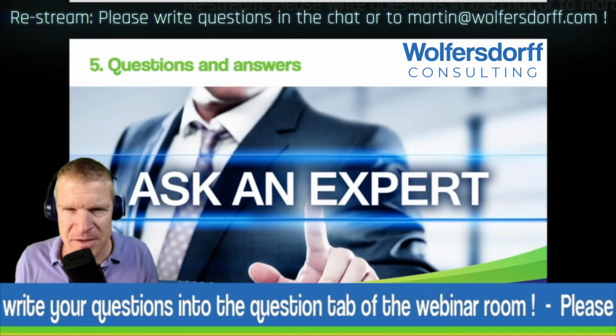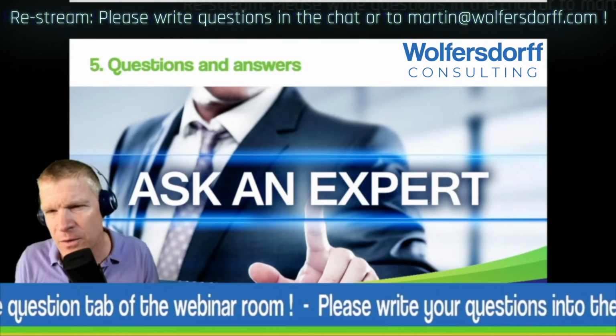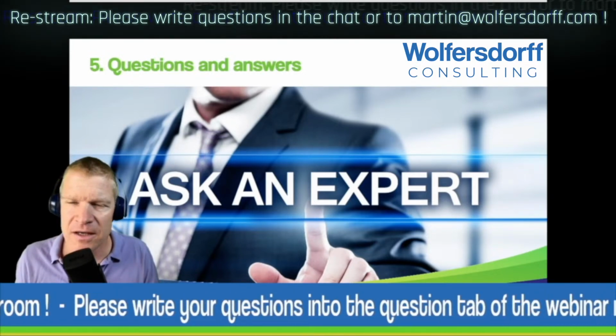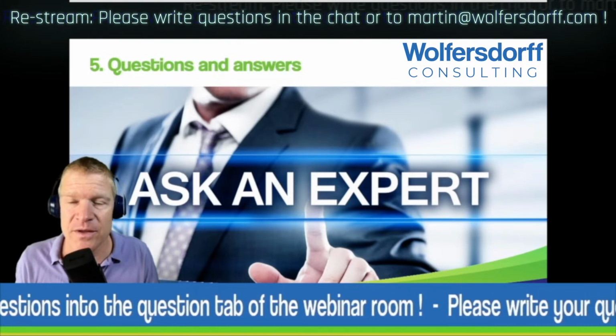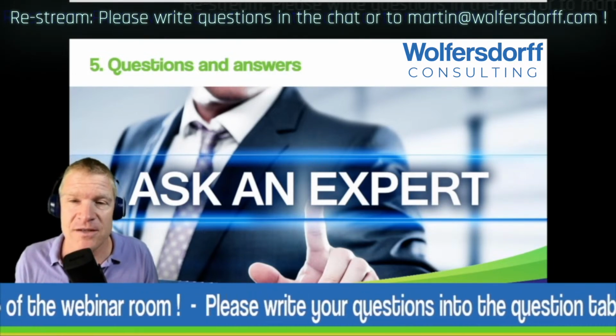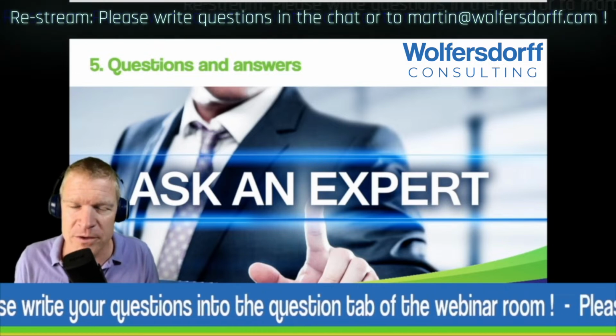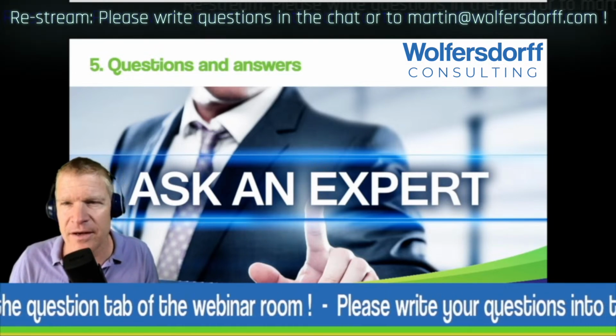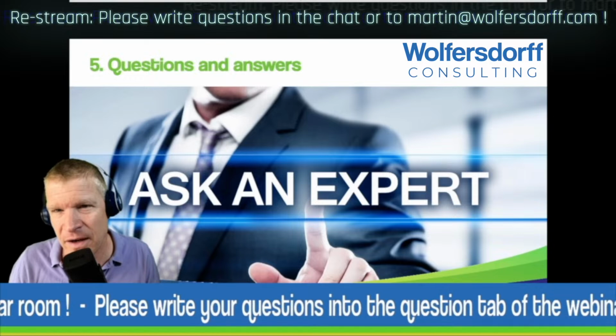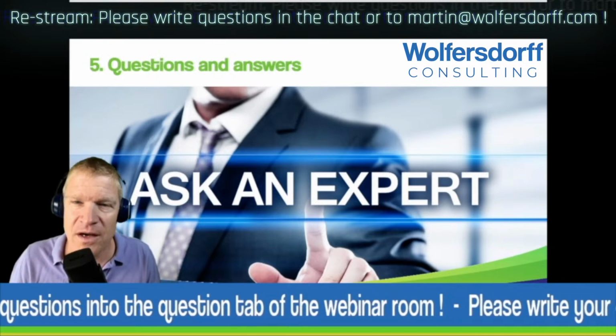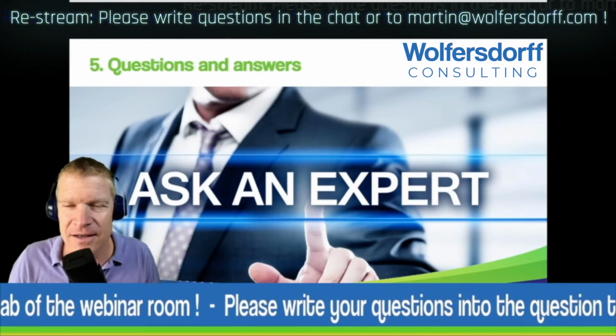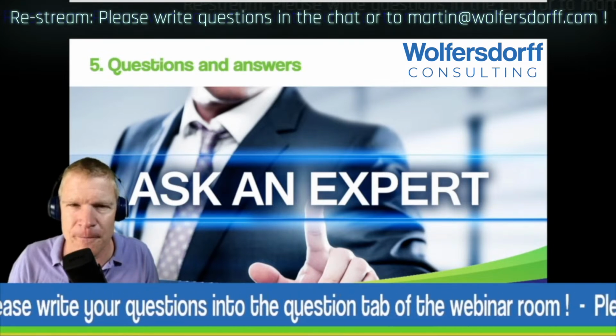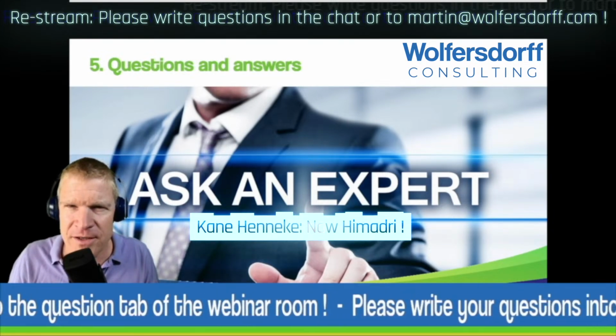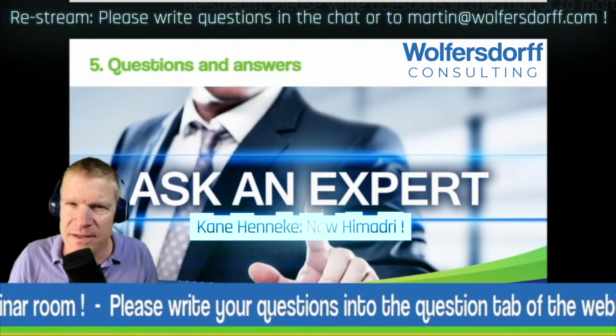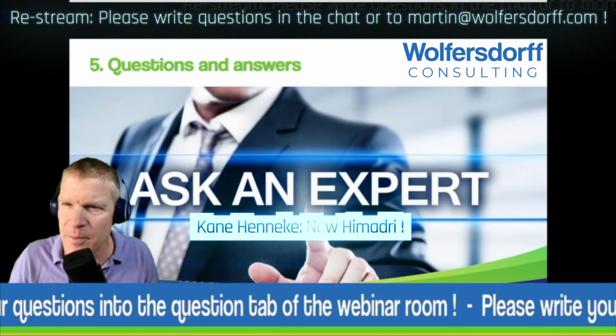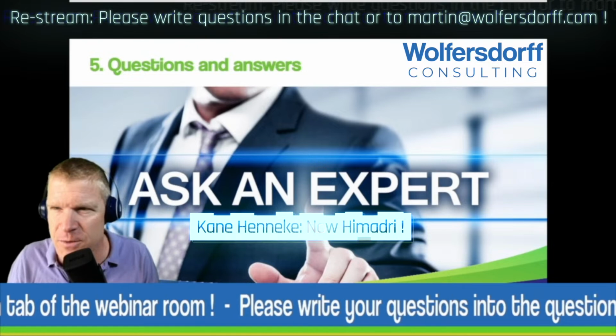Ravi from Capital Carbon: is there any difference in tint factor between powder and pellets of RCB? No, they shouldn't, provided that you can disperse the pellets as well as you can disperse the powder. So there shouldn't really be a difference. If you have pellets too hard and you don't disperse, you will certainly see a lower tint factor. That's for sure. Kane from Orion Engineered Carbons: tint factor with powder and bead depends on the ability to disperse properly. That's just what I said.